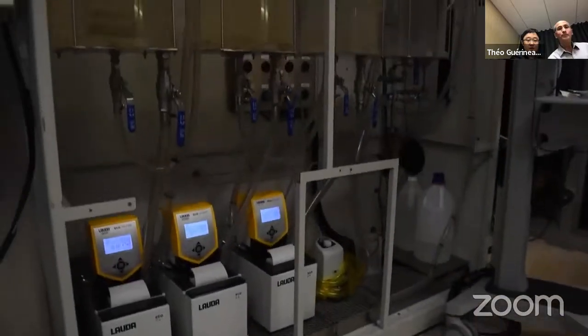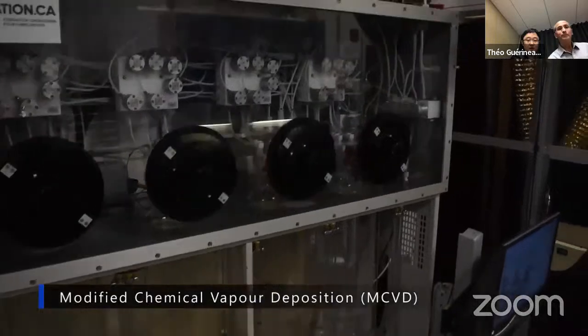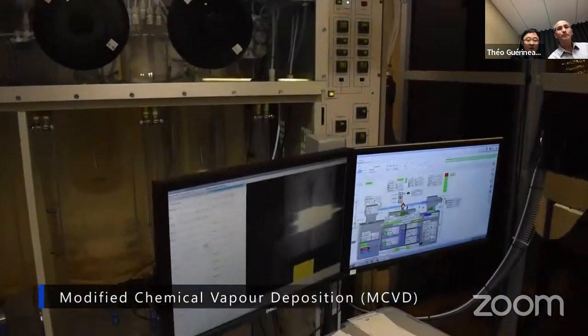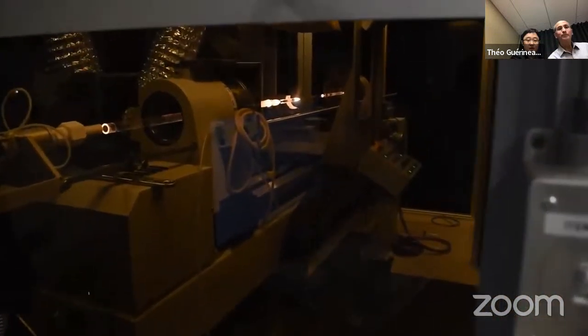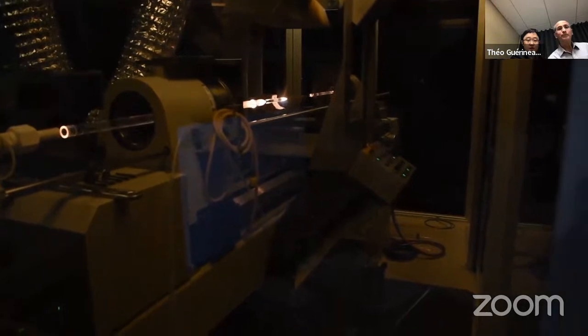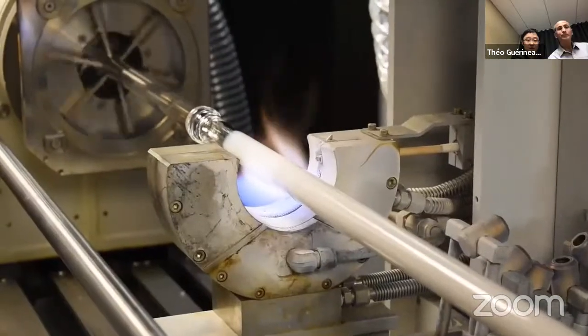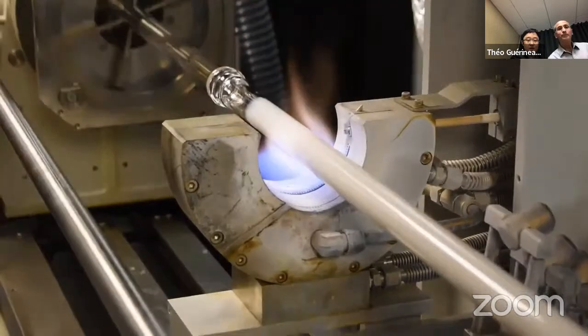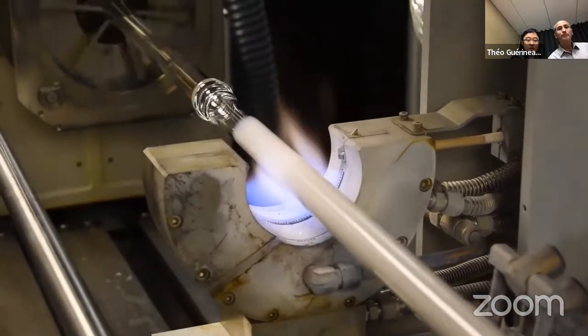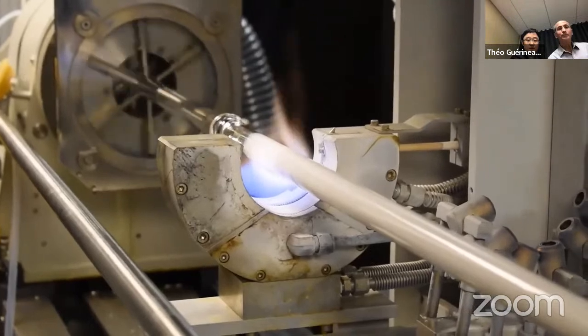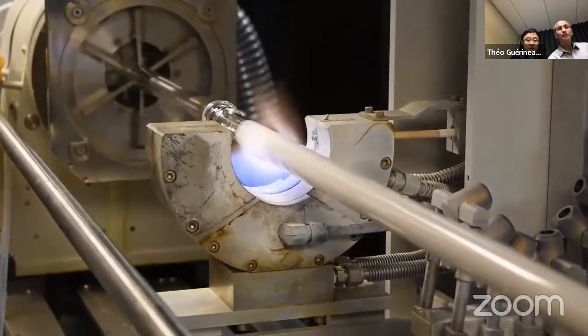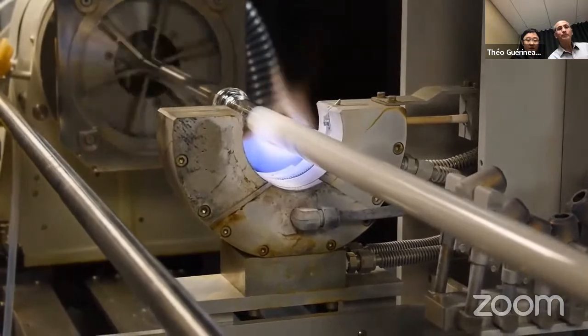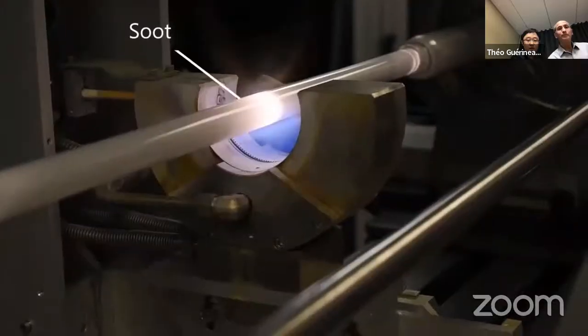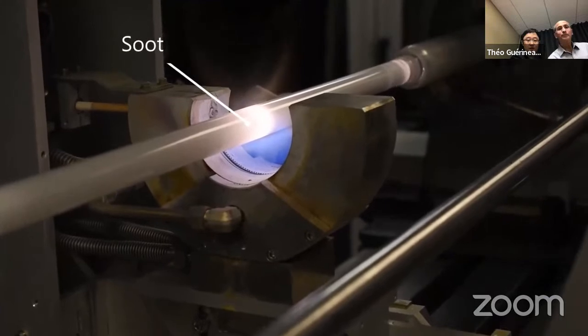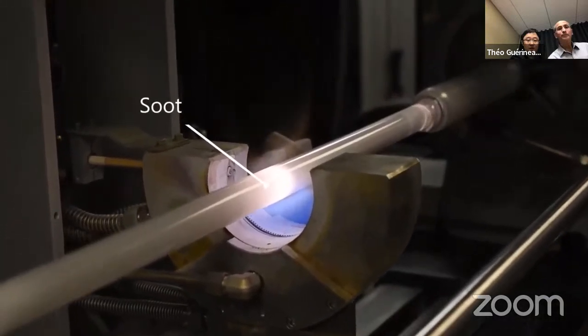In the modified chemical vapor deposition process, also known as MCVD, precursors with ultra-high purity are deposited in the inner part of an equally high-purity silica tube to build a preform which will be drawn into an optical fiber. The volatile precursors will form the core of the fiber, whereas the tube will form the fiber cladding. A controlled mix of volatile precursors of aluminum, phosphorus, silicon, and germanium allows the precise control of the optical properties of the fiber. As the mixture is heated, it forms a deposit known as soot.